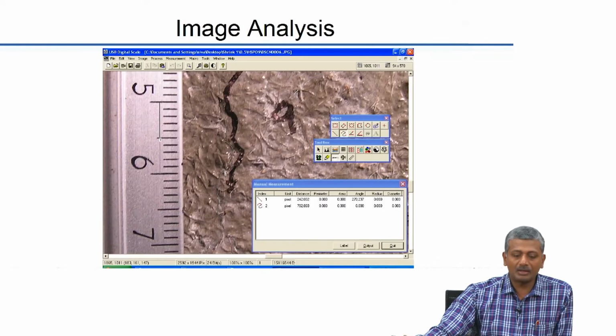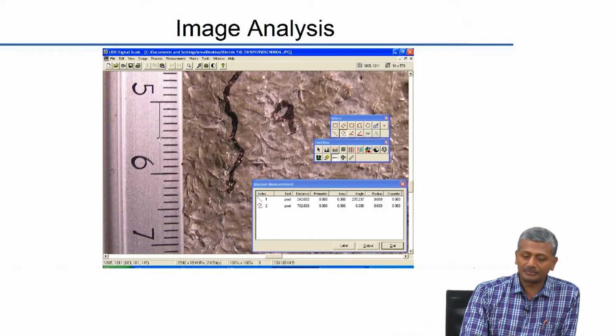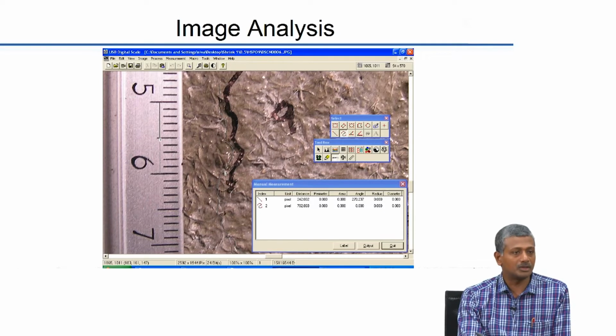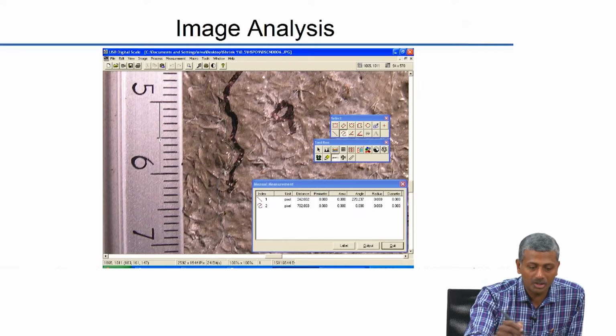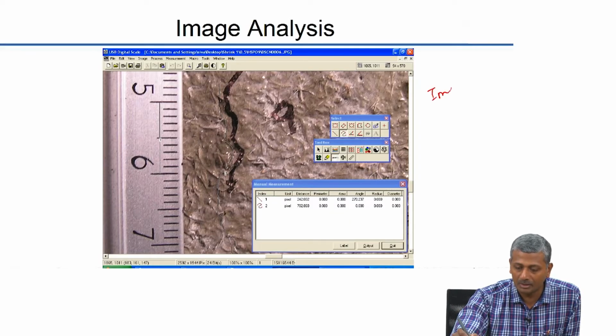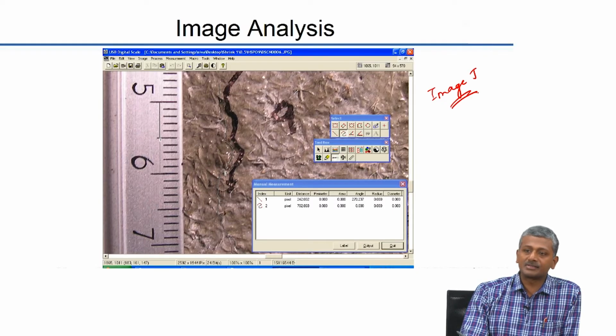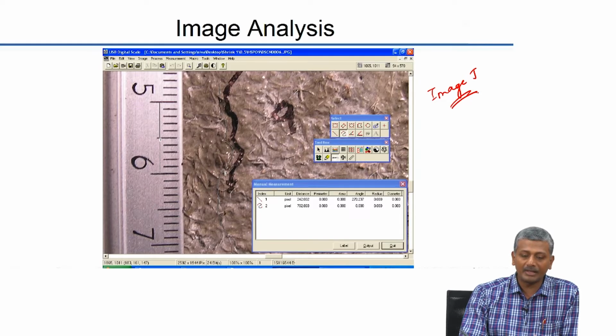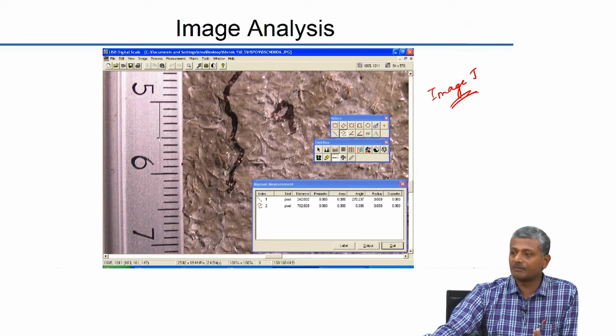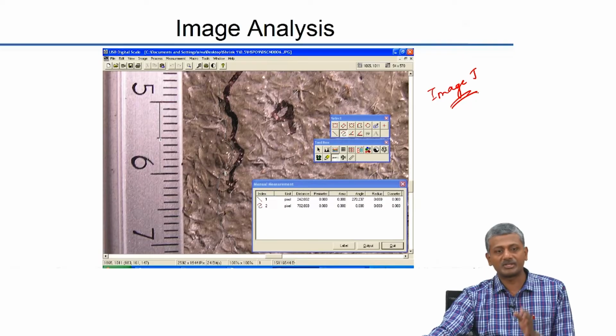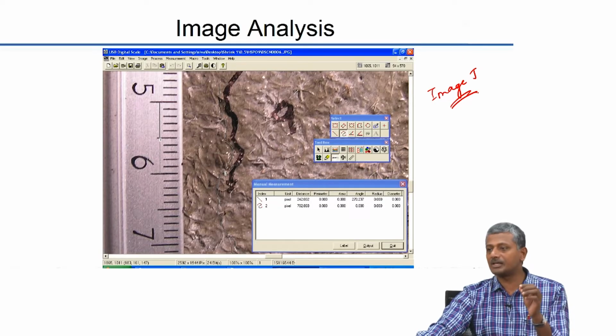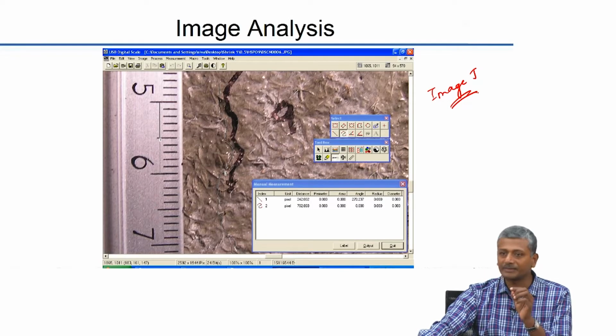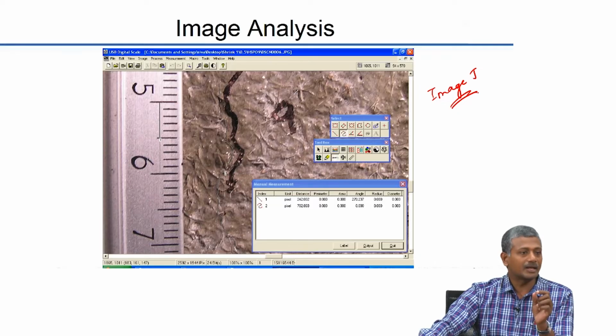And based on this, we did some measurements on the actual crack length using the tools available in the image analysis software. This is software that was available for free on the internet. It is called ImageJ. So, you can do the analysis in terms of determining lengths and size of different types of features. We determined the length of the crack, and we also determined the average crack width by taking crack measurements at different locations. Of course, you can imagine that when you deal with very fine cracks, you can't just visually take the crack width readings.